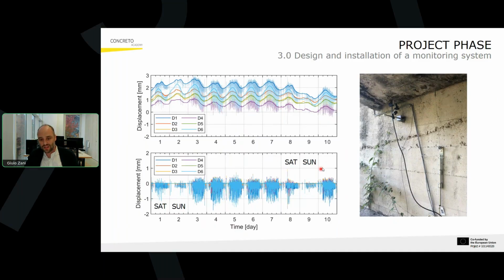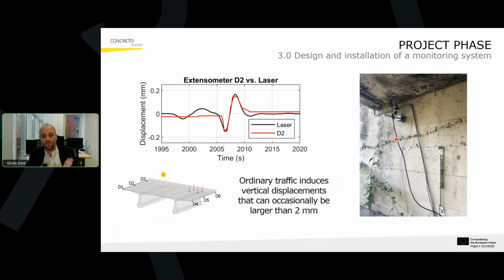You can see that on the days with the least traffic, Saturdays and Sundays, we have smaller displacements because we don't have large trucks. We also validated these measurements, since this was made with a static monitoring transducer, with a laser sensor, which is able to obtain information at a higher sampling frequency in a more precise way. From these, we observed that the measurements we obtained from the static transducer are pretty comparable to the ones from the laser. In some cases, we lost some part of the information because of internal friction effects inside the transducer, but we were able to assess that ordinary traffic induces in this particular bridge displacements which can occasionally be larger than 2 millimeters, about 2 millimeters being the threshold for these vertical displacements.